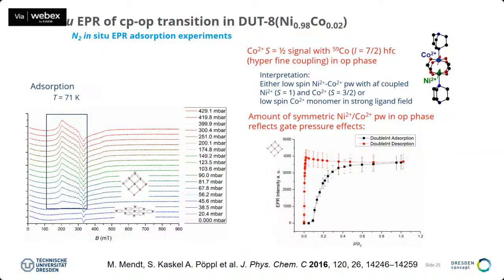When it's contracted, there's no signal because there's some asymmetry and the signal is not detected, but then when it opens up, you can see that this signature follows very much the adsorption isotherm of this kind of material.